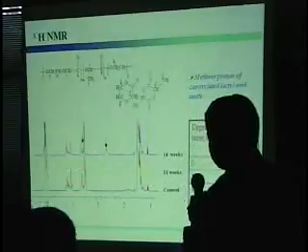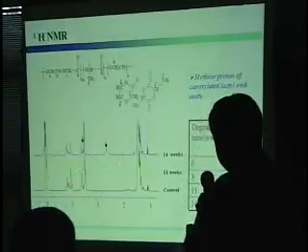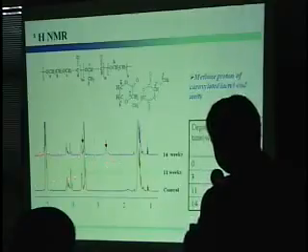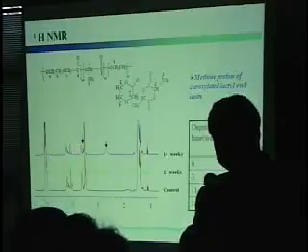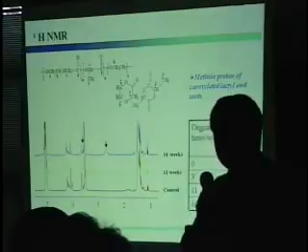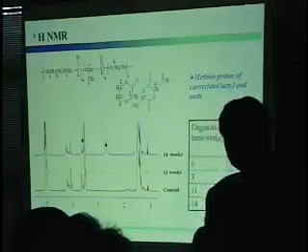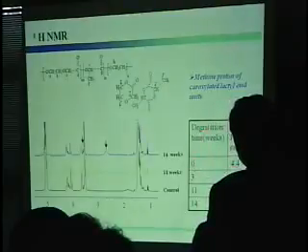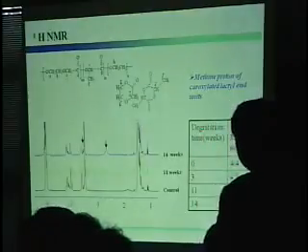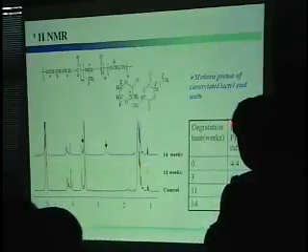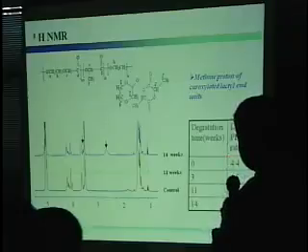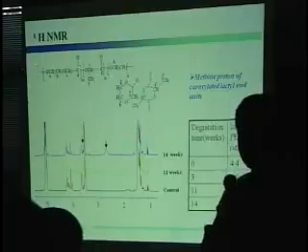Next slide, please. This is the proton NMR spectra. Here, in the degradation time, new peaks appear, and here also a new peak, and the number of peaks increases. Also in the proton NMR spectra, the ratio of exactly this, the L-lactide and PEG only, was considered. The ratio of these two parts also increases in the degradation time, which also shows the hydrolytic degradation of the copolymer.